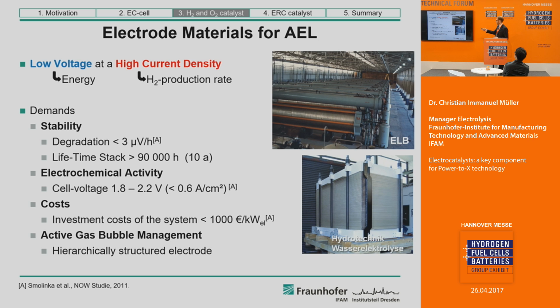So there are some demands for such an electrode. The degradation rates have to be very low, the stack lifetime should be very high, and also the electrochemical activity should be in the range between 1.8 and 2.2 volts at a current density up to 0.6 amp per square centimeter.